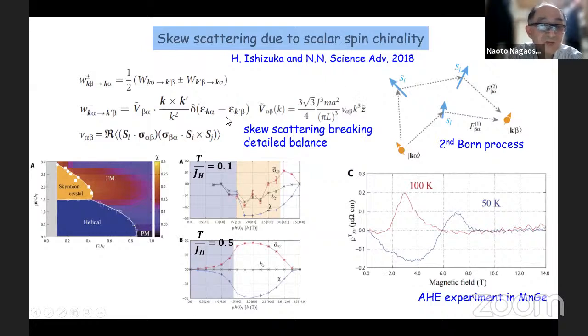So this is one of the very well known mechanisms for the anomalous Hall effect. But the new proposal here is that this scalar spin chirality leads to the sigma xy. So this is a comparison with the experiment in the theory, and the Monte Carlo calculation gives this scalar spin chirality for different temperatures. So in the case of low temperature, you have a negative contribution, and near TC we have a positive.